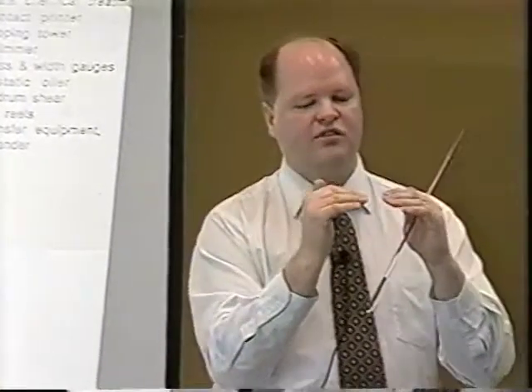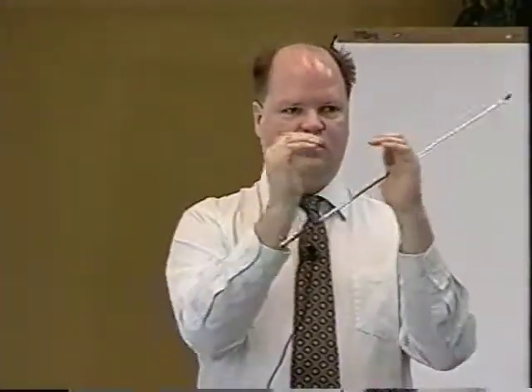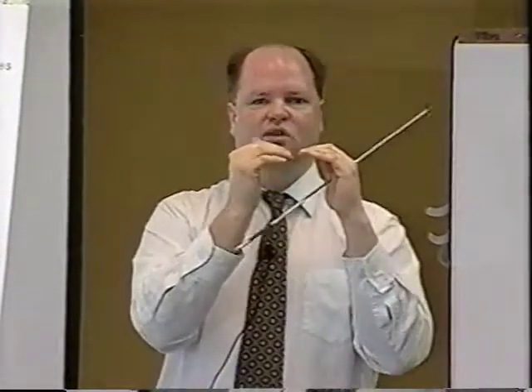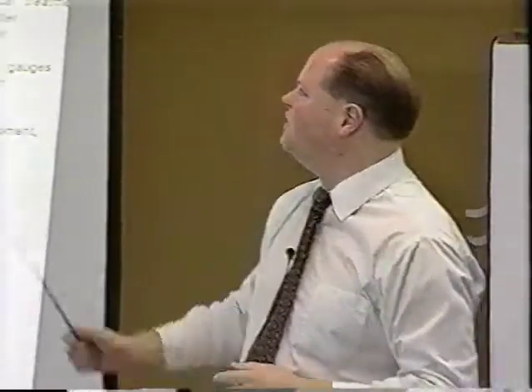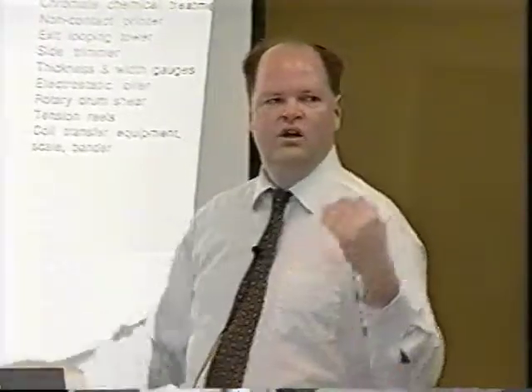There's like 8 different degrees of motion with these air knives. It can move closer to the strip. They can move higher above the bath or lower. You can tilt them this way. You can get like an angle effect if you wanted to try that. You can skew them this way. If you see one edge of the strip is heavier than the other edge, maybe they're a little skewed or something. So there's a lot of different ways to adjust the coating weight in order to get a nice uniform coating.